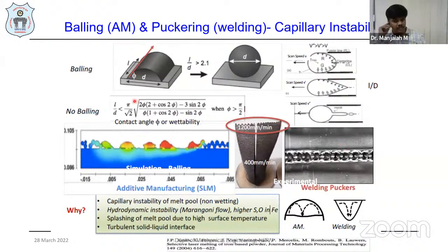Similarly, these kinds of balling effects are going to occur because of the various deposition speeds. You see at 1200 millimeter per minute, these kinds of balling effects. This is because of the instability in the melt pool profiles. This is because of non-wetting and hydrodynamic instability because of creating some Marangoni effects, and splashing of the melt pool at the higher surface temperature as well as the turbulent solid-liquid interfaces. Because of these things, the balling effects are going to occur.